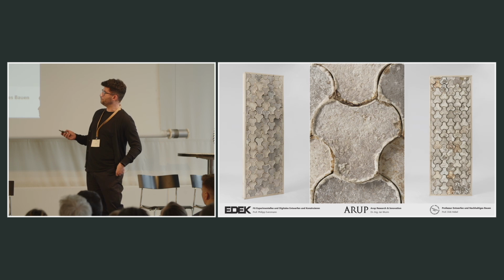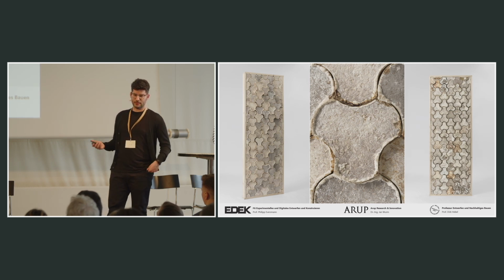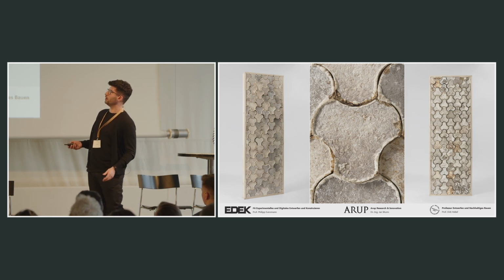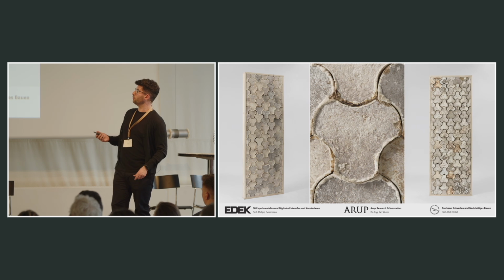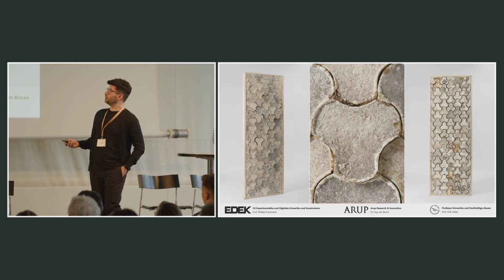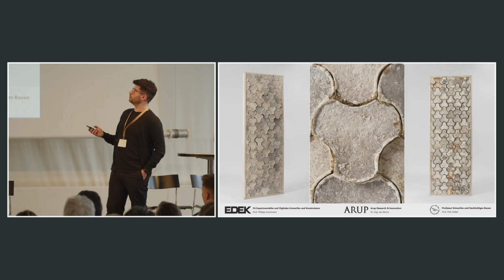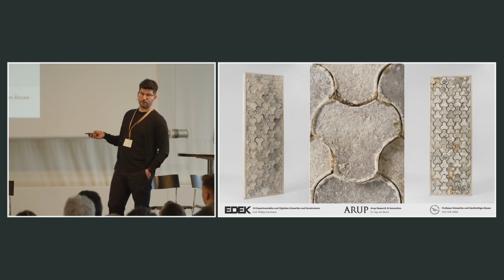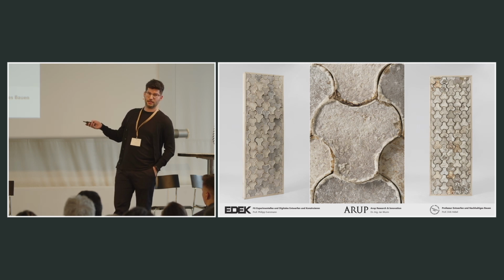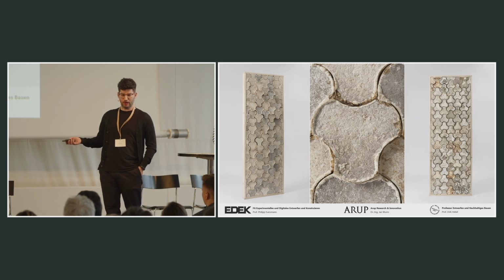So the resulting system is composed of around 100 blocks that compose a 2.40 m wall. And what is interesting is that these blocks are held together exclusively by the outer timber frame. And so by removing the frame, we are able to fully disassemble this wall and reuse it into a different